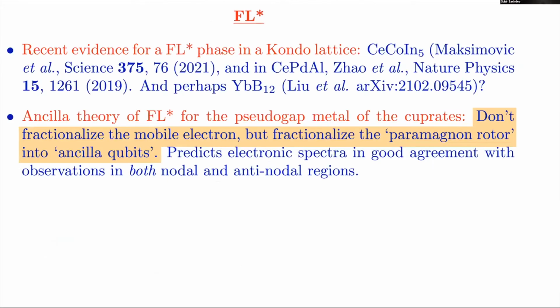Okay, so that's the end of the main part of my talk. So I first reviewed results on the FL star phase in the Kondo lattice, and I presented a new theory for the FL star phase for the pseudogap metal phase of the cuprates. And the bottom line can be summarized in a couple of sentences. First of all, don't fractionalize the electron, fractionalize the paramagnon. So fractionalize the paramagnon into two sets of spins, one of which hybridizes with the conduction electron, just like in the Kondo lattice, and the other forms a spin liquid. And that gives you a completely controlled theory of an FL star phase with an explicit wave function.